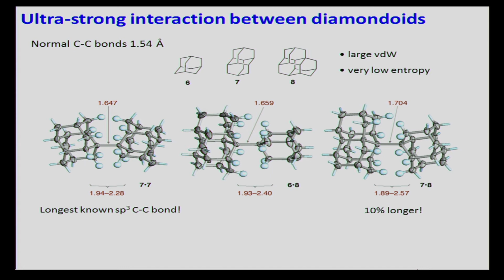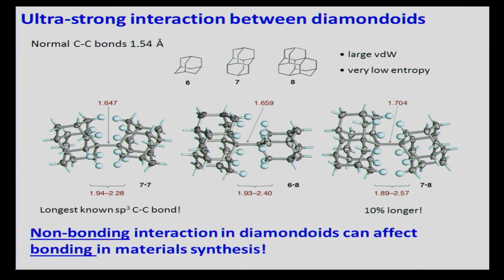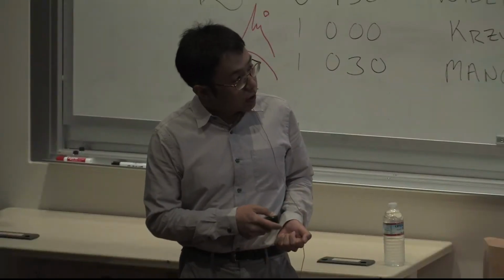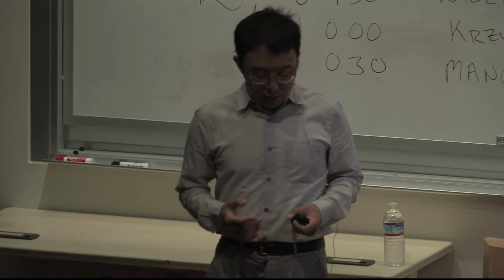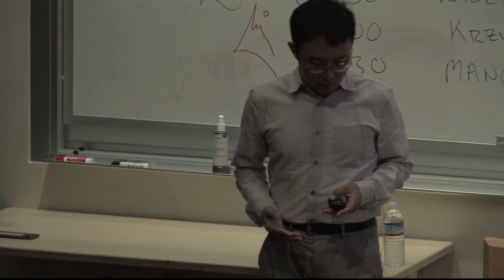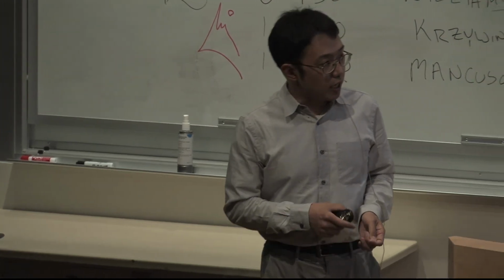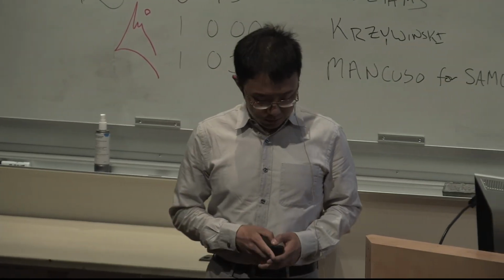And the reason is that these two diamondoid molecules have a very strong attractive force between them, so this force compensates for this ultra-weak carbon-carbon bond that links them together and holds the bond together to make this species stable. And the revelation we have here is that this non-bonding interaction between the diamondoid molecules is so strong that it effectively influences the behavior of the bonding formation in these molecules. So a non-bonding interaction that affects the bonding behavior is something that nobody has ever seen before, and diamondoid is really the key material to enable this.